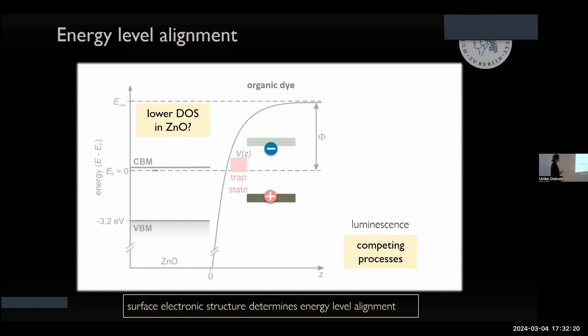However, I have to say, as zinc oxide is so n-type doped, there is not much room for electron traps, more room for hole traps, because all the defects below the Fermi energy are already occupied. You cannot put another electron there. This is something that is very often forgotten. And then of course you can also have polaron formation, trapping at the interface through hybrid excitons, which is the last option. The electron goes into the zinc oxide and then it cannot leave the interface because the hole is still too attractive.